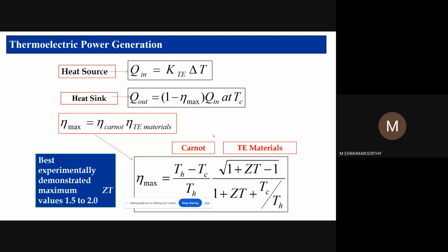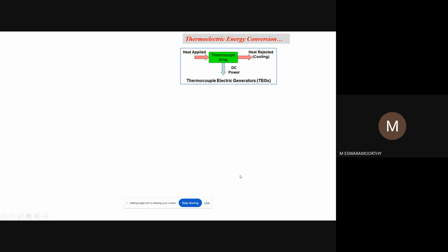The best experimentally demonstrated maximum ZT value is 1.5 to 2, and that value is going to be reached here. So once you know the hot side and cold side temperature, this maximum efficiency will reach around 25 to 30% without any hesitation.